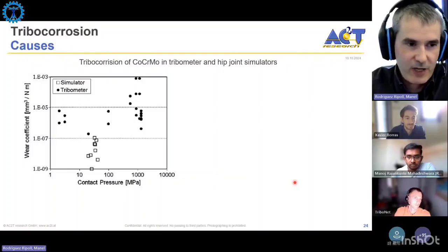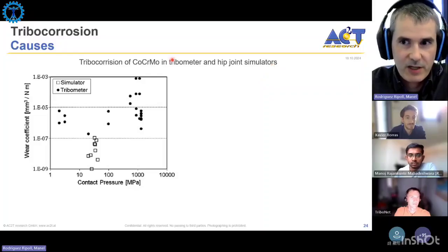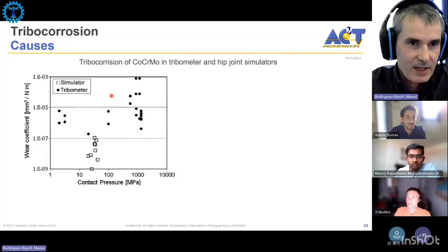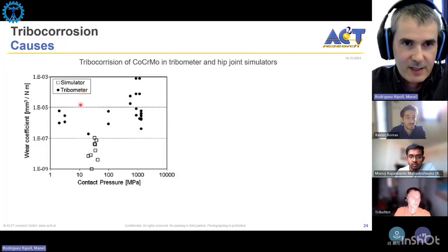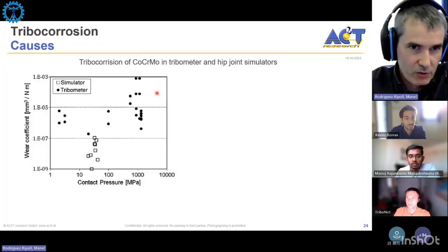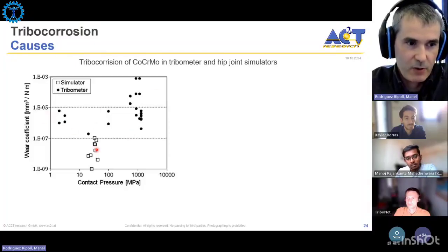And probably you can figure out if you have followed the last slides. So there is this very nice paper from Stefano Misler and Ana Muñoz, where they make a big assessment of different tribocorrosion experiments performed on cobalt chromium for hip joints using model experiments, tribometers and simulators. And you can see that as a function of the contact pressure, there is a certain trend to increase the wear, but it's not really always the same. And you can see that the wear rate in a tribometer is typically much higher because usually you have point contact, and on the simulators you have more conformal contact.